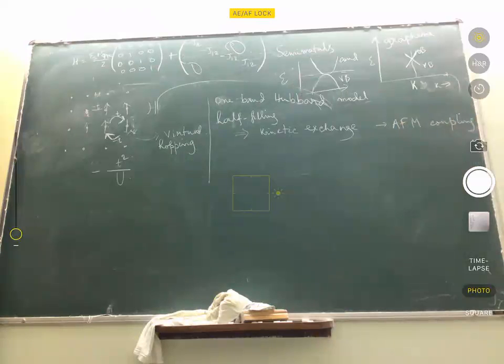So that explains why materials like cobalt oxide, and quite often these Mott insulators, turn out to be antiferromagnets. And cobalt oxide is an antiferromagnet. Okay, so two things happening here: metal insulator transition because of electron correlations and an associated magnetic ground state. So magnetism is not some standalone phenomenon. It's a result of electron correlation effects.